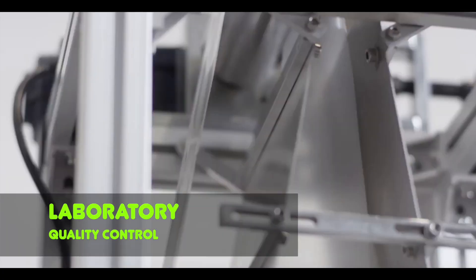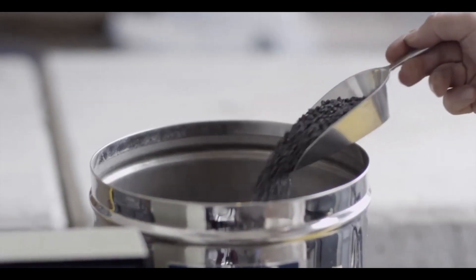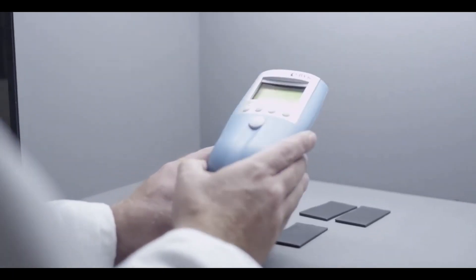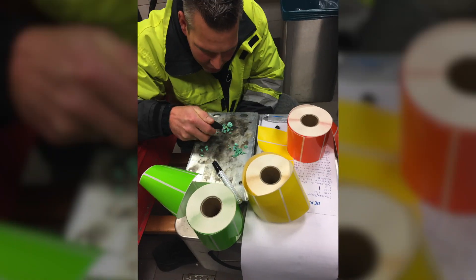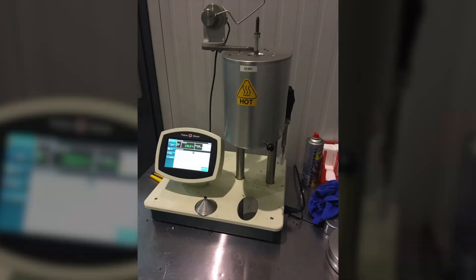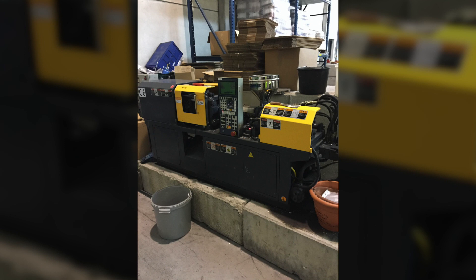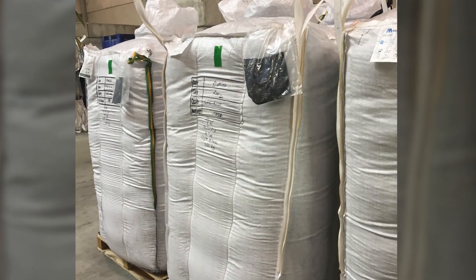And how without its own laboratory and quality control? On a corporate video, this is always people in white coats in sterile rooms. In real life it's a little simpler, but still great enough. Quality control begins right in the locker room, just because there are wash basins and water there. The managing director himself does this very often. Visual inspection is carried out — color, smell and buoyancy are checked. Melt flow index is measured in a separate room, and there is also a mini extruder, a mini injection molding machine and a mini blow film extruder. A mini blown film sample is made out of the granulate of each big bag and placed in a special pocket.